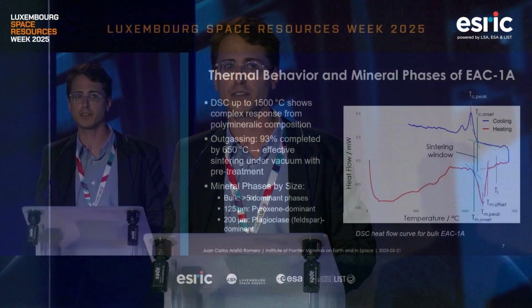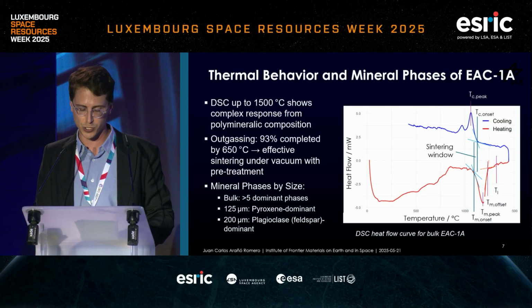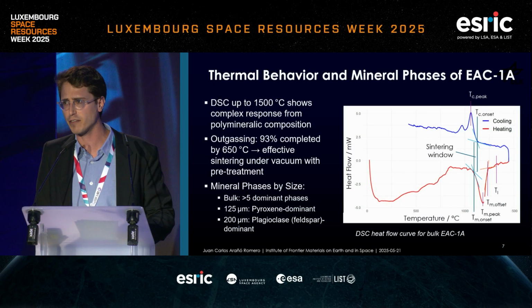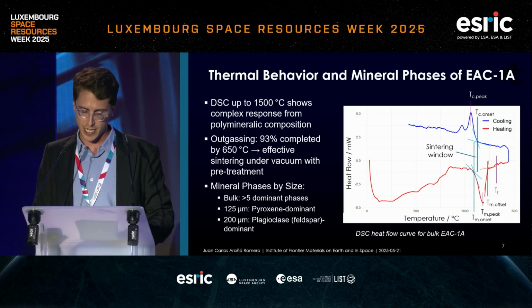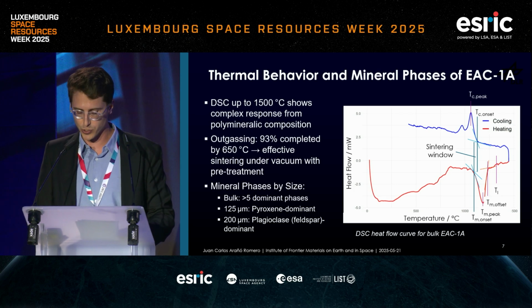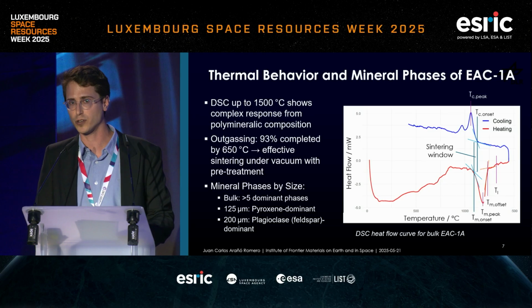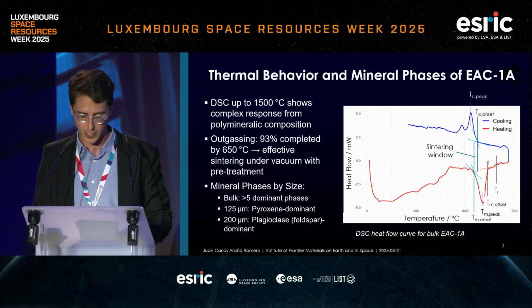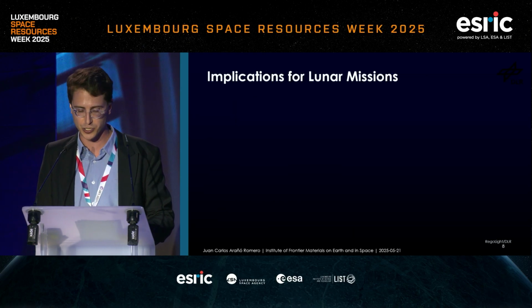Also, we ran some XRD, X-ray diffraction, in order to see the mineral phases in different particle fractions, and we saw that the bulk material has 5 dominant phases, but the finer fractions have mostly pyroxene and plagioclase. So this thermal result supports our mechanical findings, and we can show the potential for processing this material under space conditions.